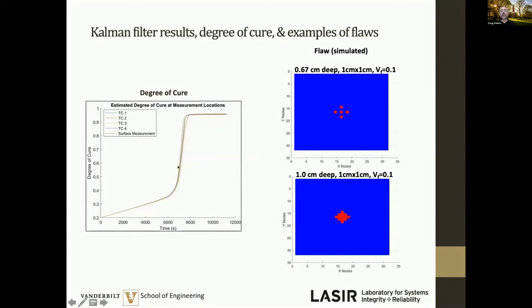So if we compare, for instance, our estimate of degree of cure of the material with the estimates that you get with thermocouples that are stuck inside this part at different depths, we see this kind of comparison where the degree of cure increases, reaction occurs, of course, very rapid changes in degree of cure, and then it cures out. And so we see very good agreement between our estimate and the estimates that you get within the part with temperature measurements that are being made by thermocouples.